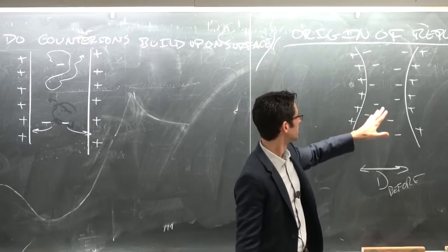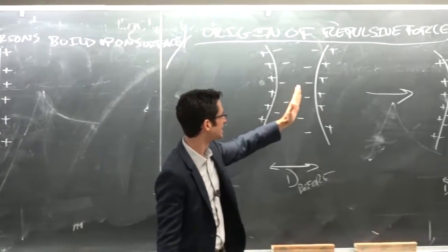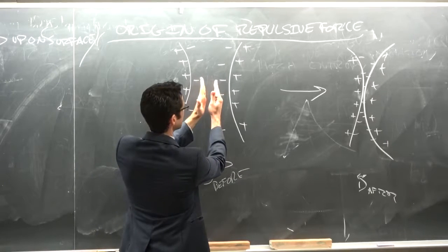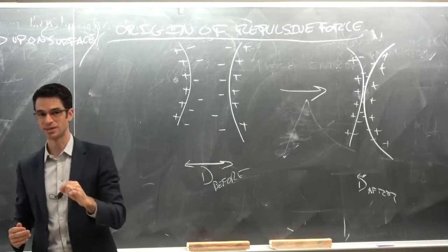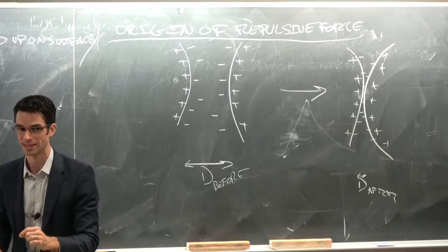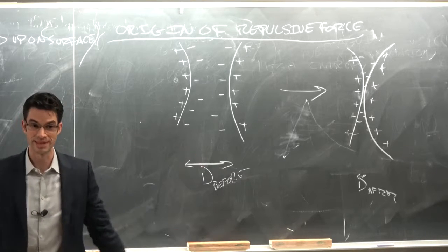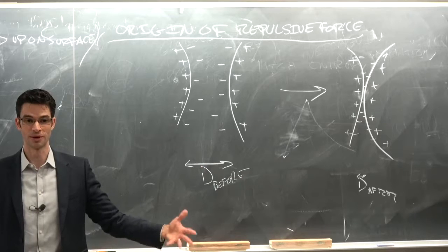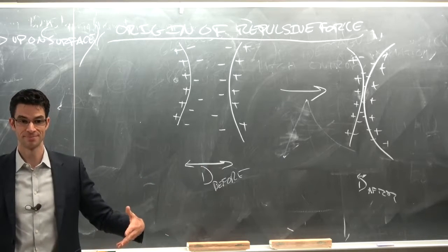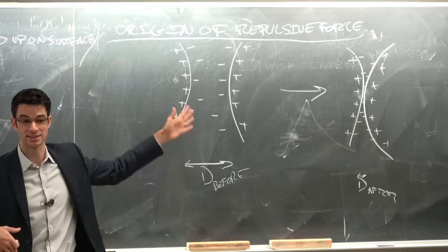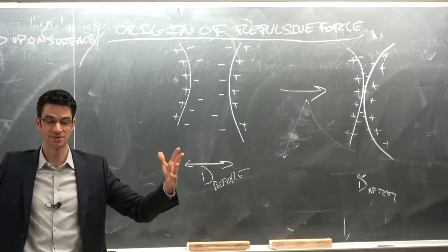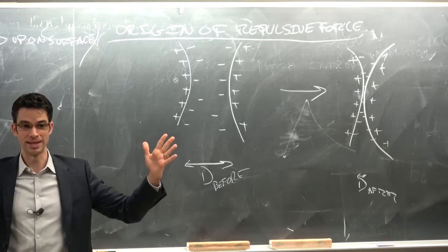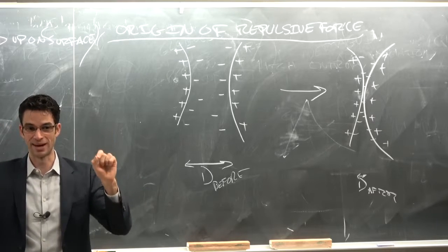And therefore, what happens in that case is that the counterions get closer to the surfaces because it's less entropically unfavorable to confine them if there are more to begin with, because there are more counterions around than there are coions on the surface. You have lots of microstates available, lots of entropy, so it's okay to confine them more.